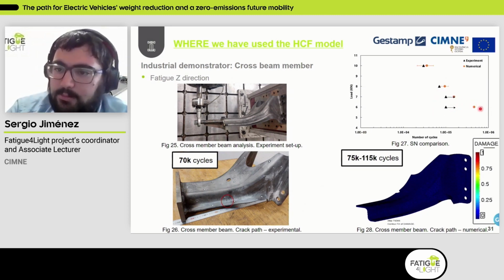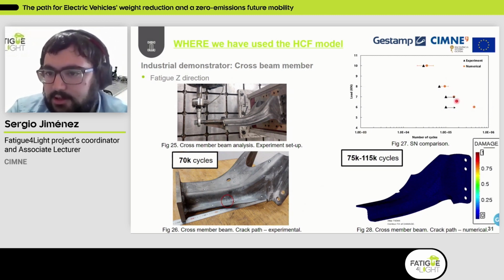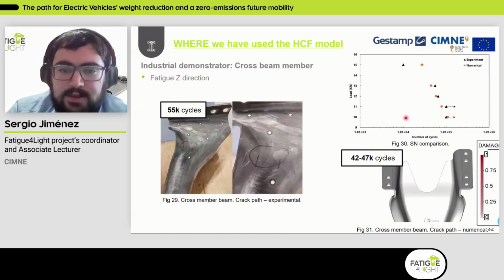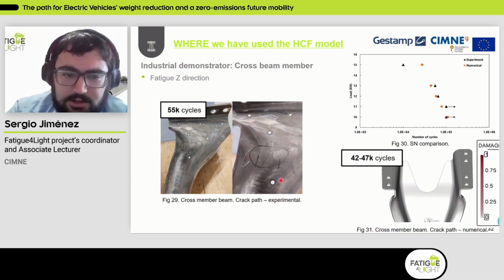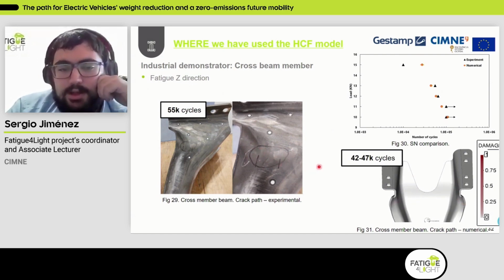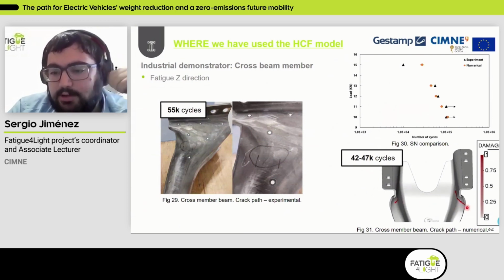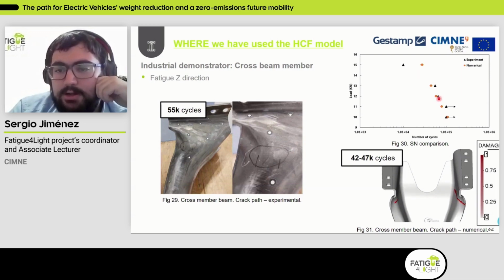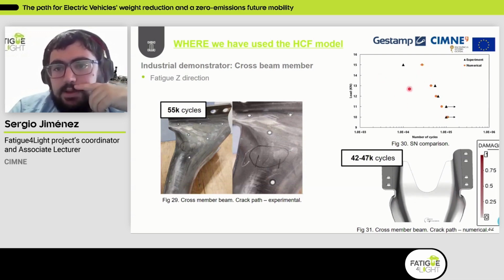We are measuring failures from the simulation point of view, but they take place after the maximum number of loads considered by the industrial partner. And then we have the fatigue response in the other direction, in the X direction. This is not correct, this is X, not Z. And from the experimental point of view, this is work done with Gestamp. So Gestamp detect the crack at the demonstrator level in this region here, which is the same type of crack that we detect at simulation level, and you can see here the correlation between simulation and the experimental results.